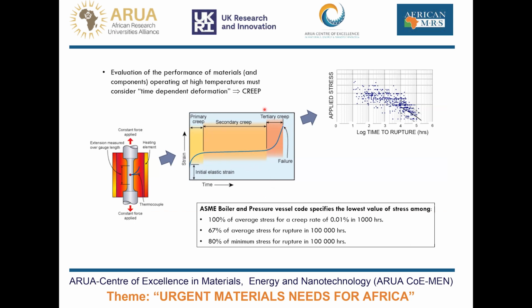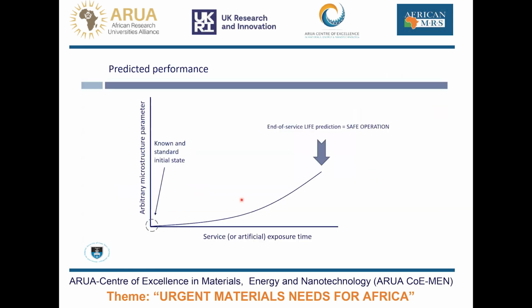And we can do that for many different tests for many thousands of hours. We can eventually determine an applied stress versus time to rupture. Therefore, if you want your plant to last, say, 100,000 hours, you know the stress limits that you should be testing or exposing your materials at in service to ensure that you don't get failure before end of life.